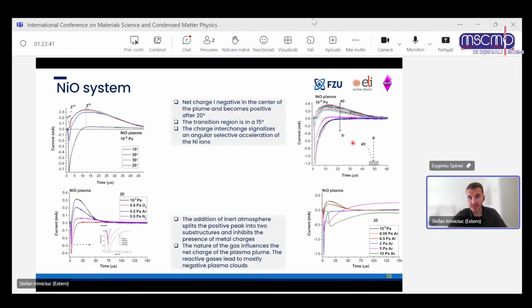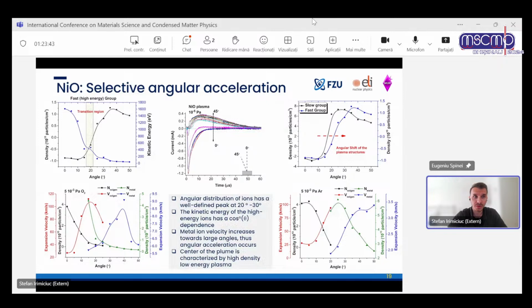And maybe something more spectacular, when we looked at the nickel oxide system, and you will see nickel, manganese, silver, these are all elements that could appear at some point in the high entropy material, but especially nickel. If we look at the nickel oxide system, we saw that actually nickel spreads towards the edges of the deposition. So in the center, we have less nickel, and the ions move to the side.